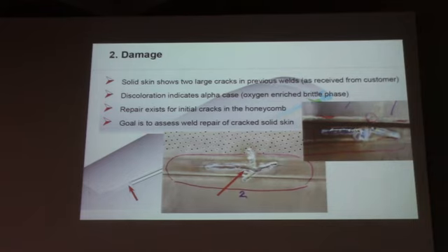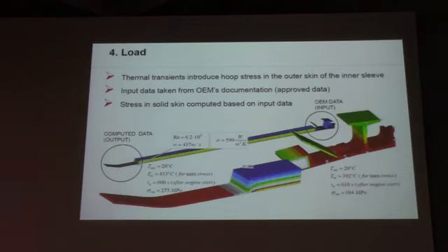So to go back to this slide about the damage, there were cracks detected and some, I would call them amateur attempts to repair it. So just welded to stop further growth of crack, which was not successful, as you can see. This is, by the way, the part we are talking about. So this initial try to repair the damage was not really successful.